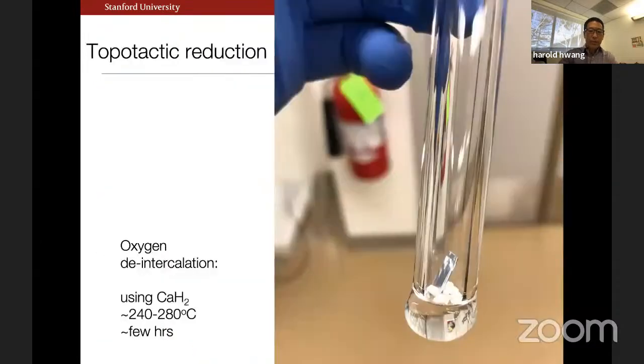And as far as the reduction reaction, it looks much more modest, but it's actually quite challenging in its own right. This is how it looks. This is a 2.5 by 5 millimeter thin film, loosely wrapped in aluminum foil. And these pebbles down here are calcium hydride, and we're using that as the reduction reagent. So we vacuum seal this in a glass tube and do a fairly low temperature reduction anneal to, again, pull out these planes of oxygen.